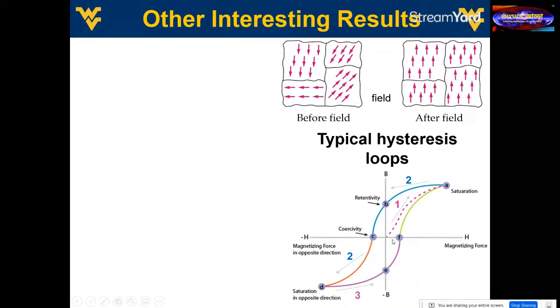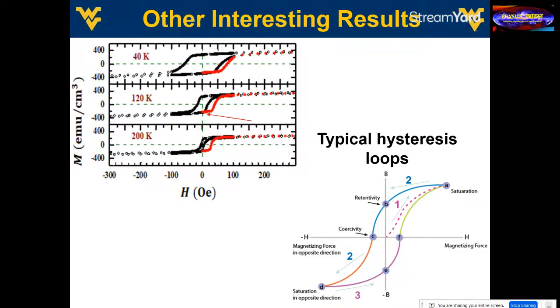And then after you apply a field, you ramp this up. Now you're in this case after the field. And of course, if you turn the field down to zero, if you have a ferromagnet, you're still going to have this alignment. It might not be as strong as when it was fully saturated. And it takes a large field in the opposite direction to get it to switch direction. All right, so that's normal. That's what normal hysteresis loops look like. Ours are similar, but a little different. So in red here, I have one, that initial starting from zero magnetic field and ramping up.